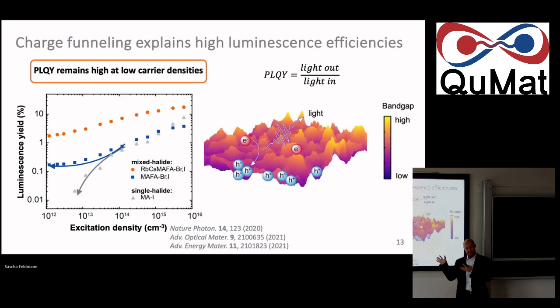And here I cut a long story short, we correlate all this with transistor measurements, with time resolved luminescence and transient absorption measurements, et cetera, to really show that what's happening is a local charge accumulation effect, where even though globally your charge carrier density isn't very high anymore if you excite with so little light, locally these charge carriers can accumulate and therefore act as very efficient hotspots to be extracted from for a solar cell or to emit from in an LED. So this charge carrier funneling effect actually enters certain regimes where it's okay to have disorder in a way, and it's not so bad.